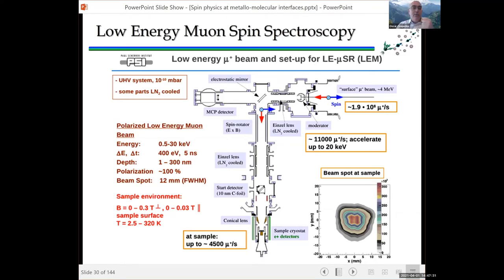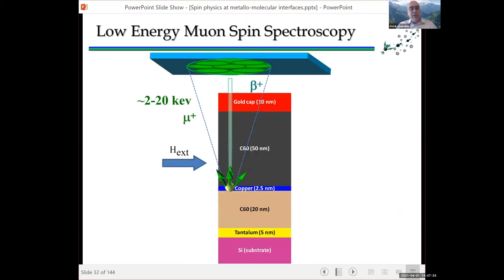So by doing that, they can control where in your samples the muons are going to stop. So think of the muon as a particle that you are going to use to probe your magnetic structure. And depending on the accelerating voltage that you impart to this particle, which has a mass roughly equivalent to a proton, you are going to implant it at different depths in your structure. Now the muons are fully spin polarized. And once they are implanted in your structure, their spin is going to precess in the local magnetic field. And after 2.2 microseconds, the muon is going to decay and emit a positron in the direction of the spin. So that means if your muon is oscillating, your positrons are also going to be emitted in an oscillating fashion.